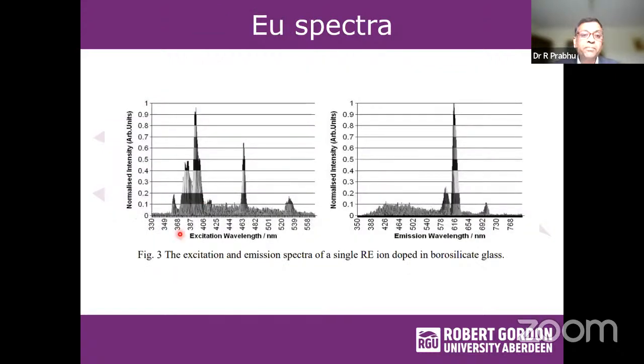So a typical spectrum from europium. You can see this is the europium glass, and this is the typical absorption spectrum from the borosilicate glass. You have the sharp absorption around 465 and a UV absorption band around 385. And again, the emission spectrum is also very sharp, peaking around 620 and a smaller one around 590. So these peaks can be used as a special signature for europium doped glasses.